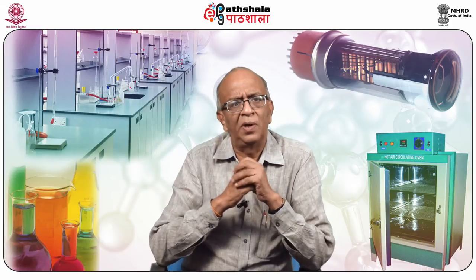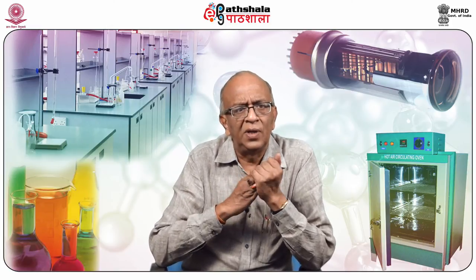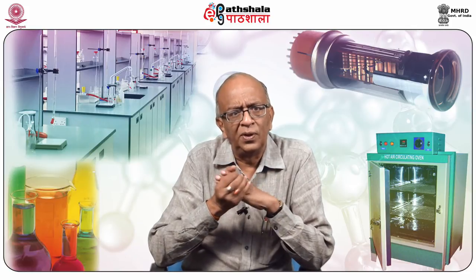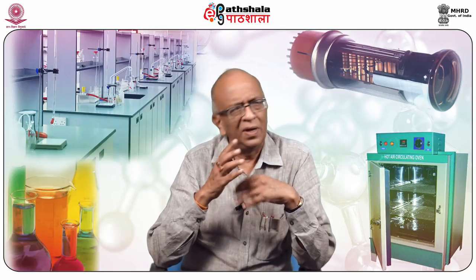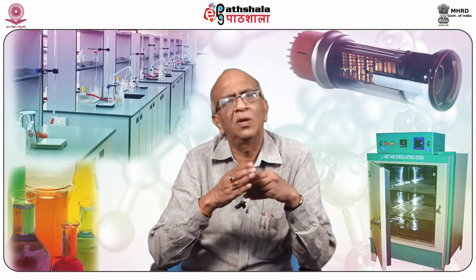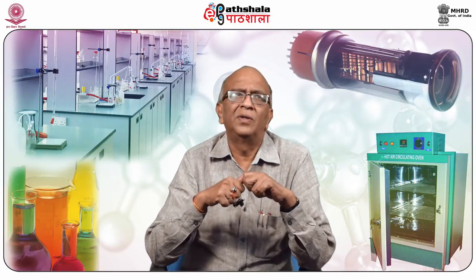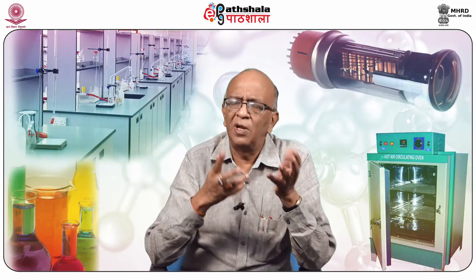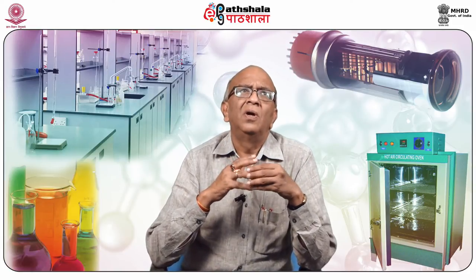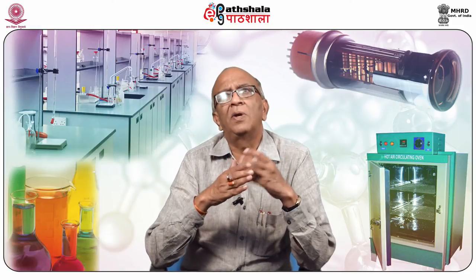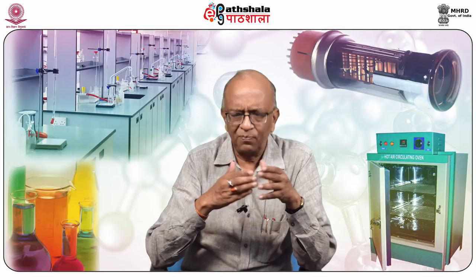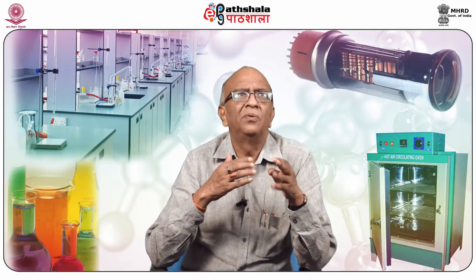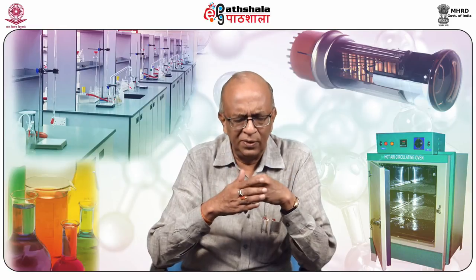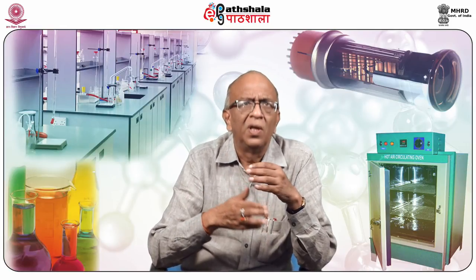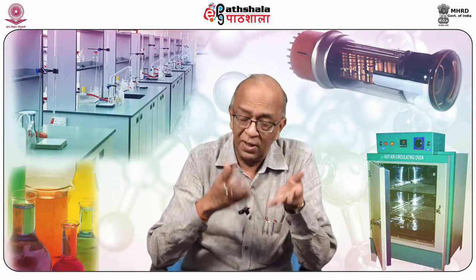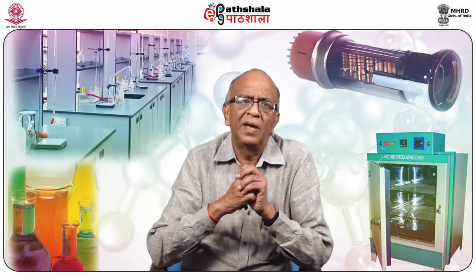Determinate errors for electrothermal atomization are frequently greater than those obtained with flame atomization due to serious matrix interferences. As we have already studied, in the case of electrothermal atomization there are interferences, whereas in flame atomization errors are less. So if the concentration is sufficient, then flame atomization is preferred. Otherwise, electrothermal atomization is preferred. By using electrothermal atomization, the technique is very sensitive, and we can go up to the parts per trillion level. More than 60 elements have been analyzed so far.